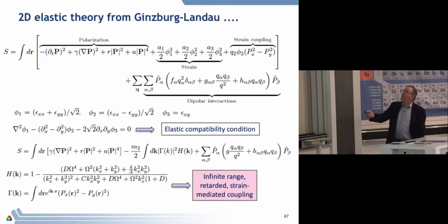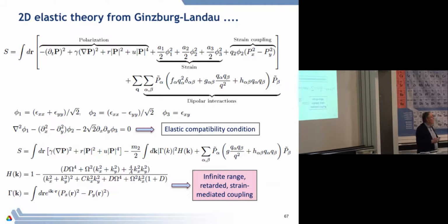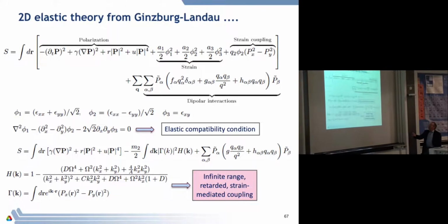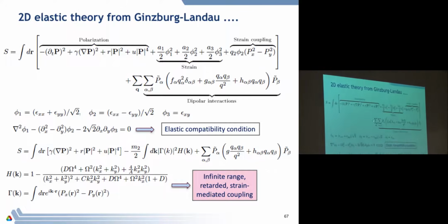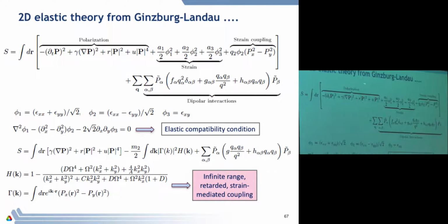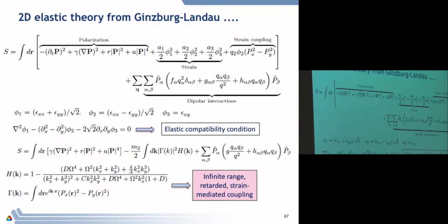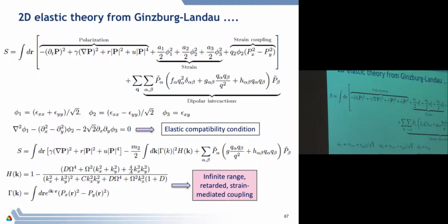So you start by thinking about your order parameter. In this case, it's the polarization. The polarization has an energy term that looks like this. There's a p squared and a p fourth. And if you know anything about Landau theory, what you will know is that if this coefficient r becomes negative, that means that the energy goes down for a little as the polarization increases, and this term will stabilize it, but there's a minimum of the polarization at finite p. Okay?